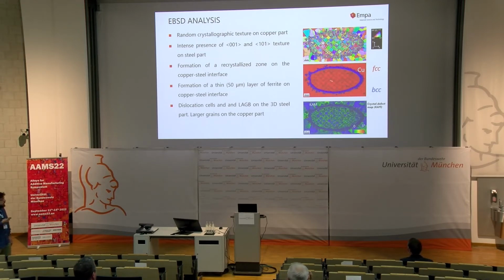Now, speaking about the phases, what we observe is that in the interface between the copper and the steel part, we see the appearance of the BCC structure. Initially, by having a look on this BCC structure, three possible scenarios could explain its appearance. Theoretically, it could be ferrite from the printing of 316L structure. However, this scenario cannot be feasible because of the specific position of this BCC structure, and based on some XRD patterns that we saw that practically only austenitic phase appears after the printing of steel. Second explanation could be segregation of chromium, but the most prominent one is that during the casting of copper, we have an indirect heating and cooling of steel, so we result in a phase transformation from austenite to ferrite.